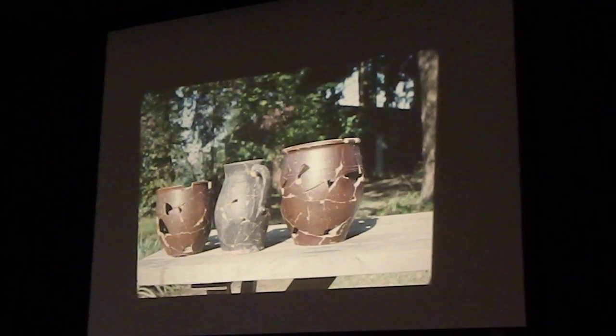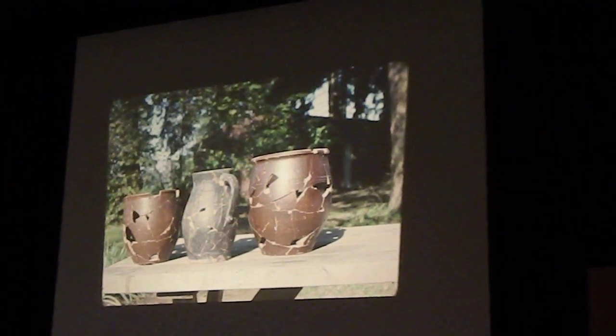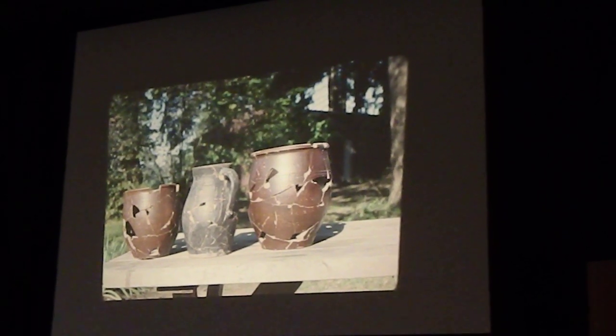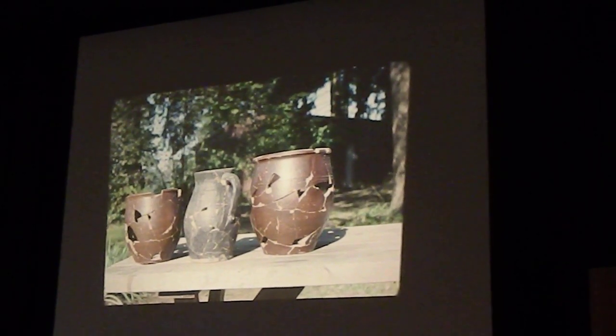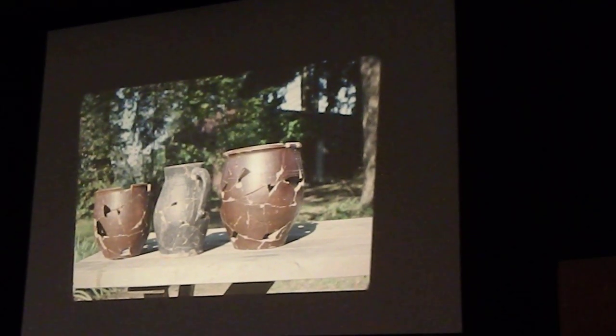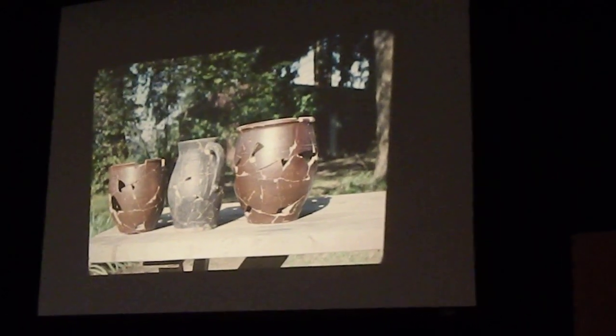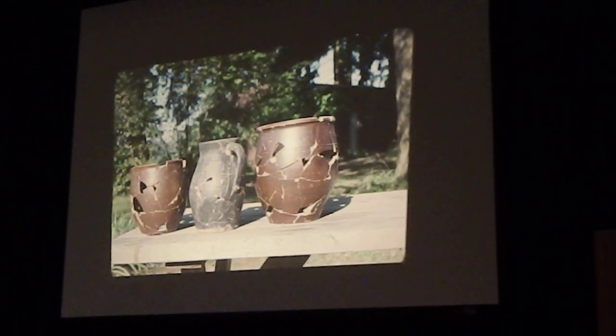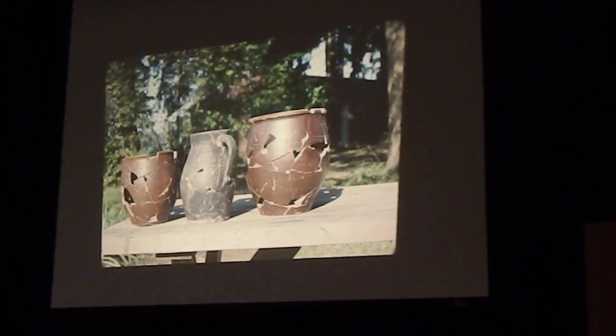And Blaine and I actually spent 2 weeks in the Midwest, and 3 of the days were spent at the Richardson site in western Indiana, and we saw the same thing there too. But basically, it was a very thin pottery. It was redware. It was 7.5% by weight of iron oxide, which made it more like a brick constitution than a pottery constitution.